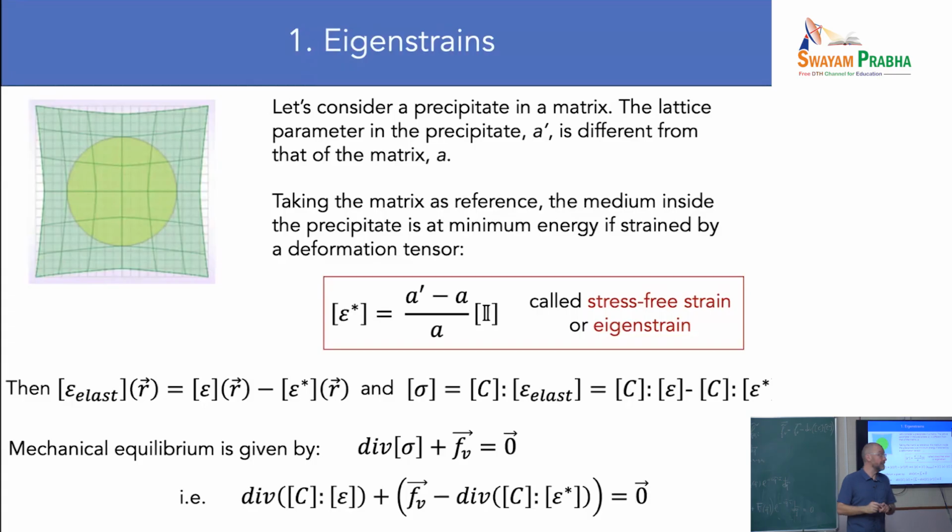So you can do it, but in many of the phase field simulations, they just assume homogeneous elastic constants. So you have to look at the paper and what they have done, if they tell you that they have accounted for inhomogeneity in the elastic constants or not. In many cases they don't, so that they can use this simple relation. That's the main limitation of what is done here, in my opinion.